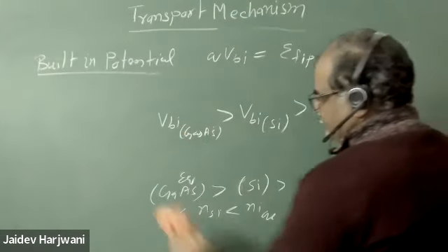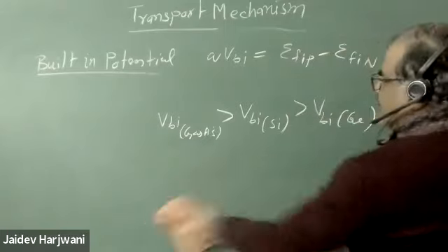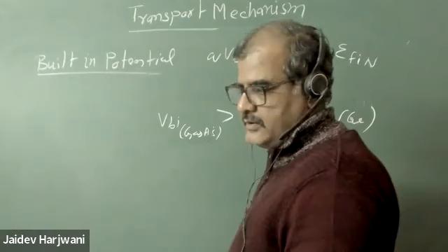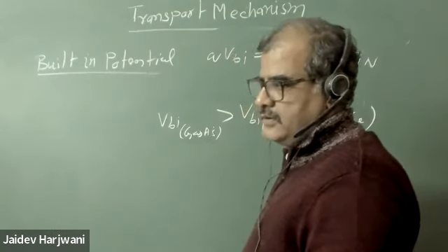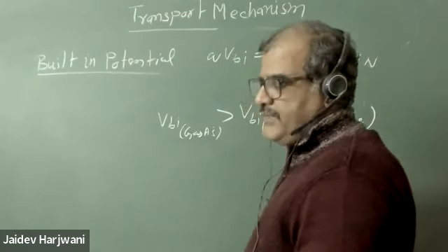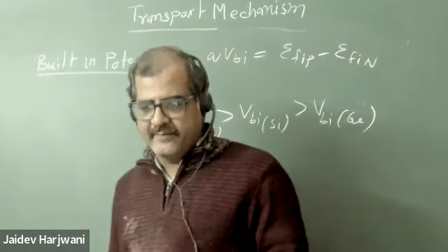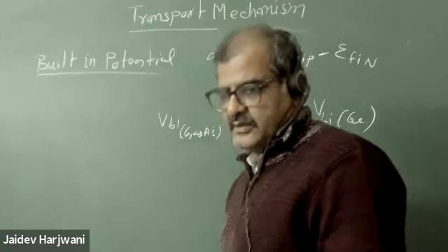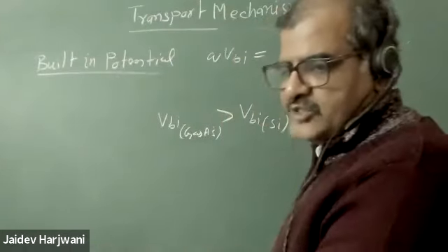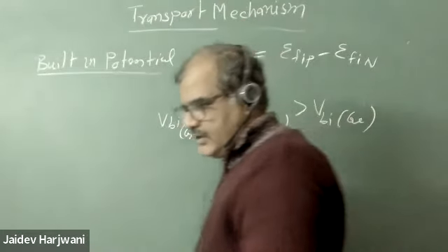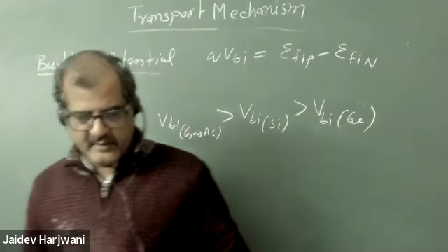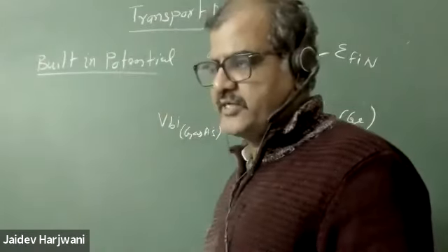Okay, so they have a higher VBI. So built-in potential. Yes. In VBI, if we leave aside Ni, the rest of the terms are constant. Yes, the P type impurity you already know is Na, and the N type impurity you know is Nd. It depends on how much doping we do, the doping concentration. Ni squared is a material parameter, inversely proportional. Ni is the intrinsic carrier concentration, which depends on temperature for any given material.